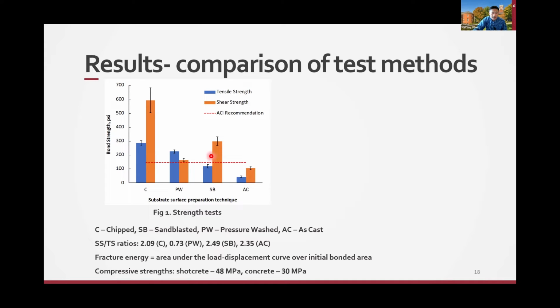Okay, so exactly why the pressure washing gives you higher tensile but lower shear compared to the sandblasting, we think the sandblasting probably generates some dust, and the pressure washing method cleans the dust from the interface, and tension maybe is very sensitive to the cleanness of the surface. Maybe that's why tensile strength is higher when you're using the water pressure washing method. For the shear, the sandblasting surface preparation maybe gives you higher roughness compared to the pressure washing method. So that's our hypothesis.